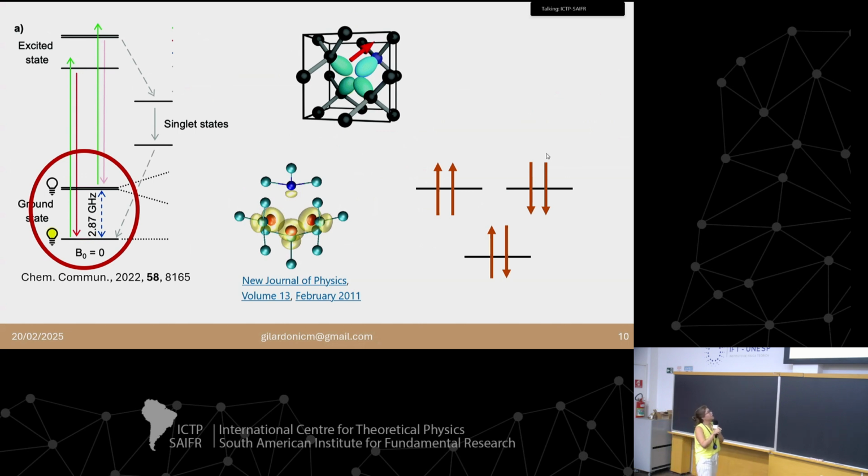Now, like I said, there's also a singlet manifold over here, right? So that's when these 2 unpaired spins actually pair up. And the rest of the optical cycle of this system is composed of non-radiative spin transitions from the triplet excited state into the singlet manifold and then back. What's special about this system is that these non-radiative transitions are spin-dependent, right? So once you start driving optical transitions within the system, you end up with the spin polarization that arises from the optical cycling between ground and excited state. Right? So optical driving of the system initializes your spin.